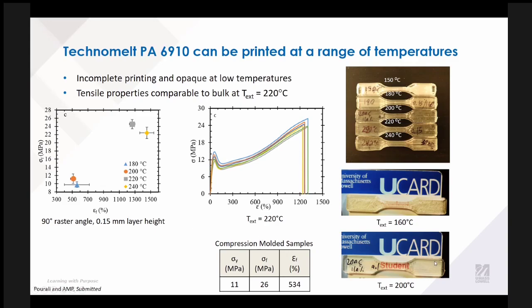We also see that samples extruded at higher temperatures are optically transparent, which is something that's cool, and they're flexible materials. So we have a lot of really interesting property combinations here.